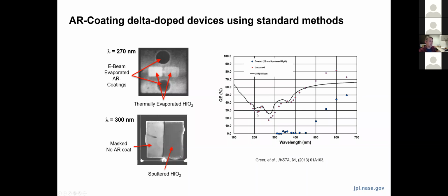There's more evidence of this in the plot on the right, which is showing the measured quantum efficiency of one of these detectors, again, with an uncoated device showing a reflection limited response, and then a device that was coated with a hafnium oxide film, in this case, that was intended to improve the QE in this 300 to 400 nanometer range, actually degraded it substantially. And so basically what was happening was either through energetic processes as part of the sputtering process, we were causing physical damage into the delta layer, essentially, and degrading the passivation, or from that X-ray exposure, a similar phenomenon.